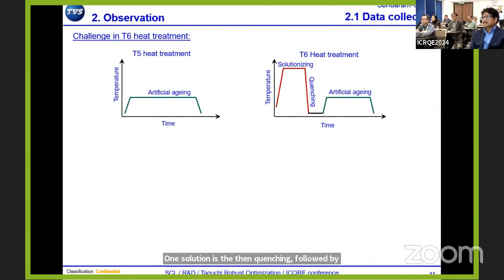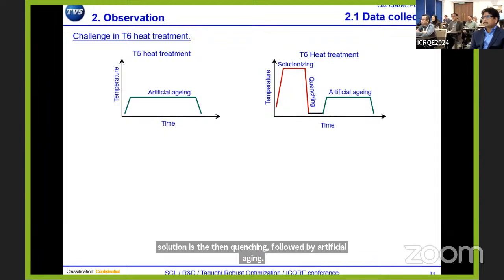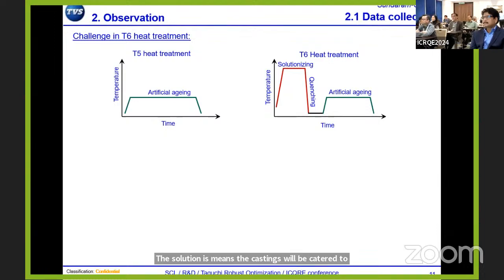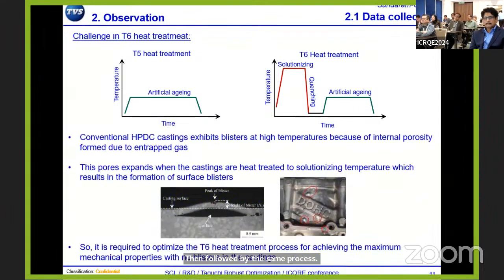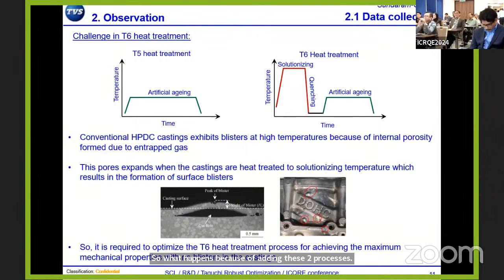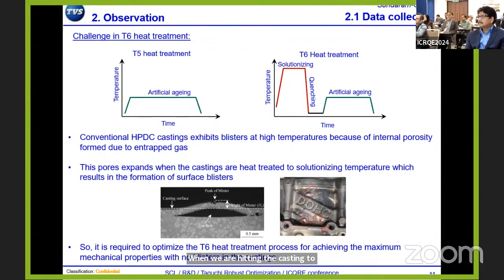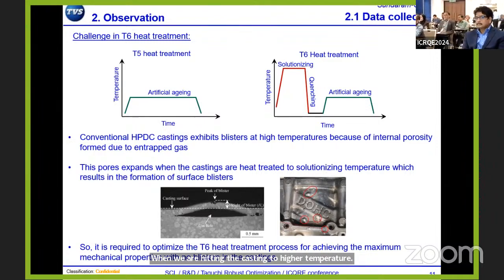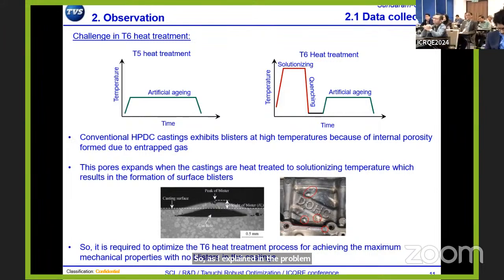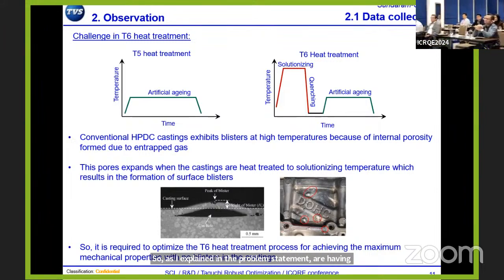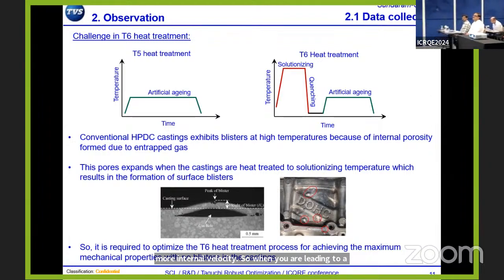Solutionizing means the castings will be heated to a very high temperature, near the solidus, then quenched immediately in water, followed by the same aging process. So what happens because of adding these two processes? When we are heating the casting to a higher temperature, as I explained in the problem statement, HPDC castings have more internal porosity. So when you heat to a higher temperature, this internal porosity will expand, come to the surface, and form blisters.